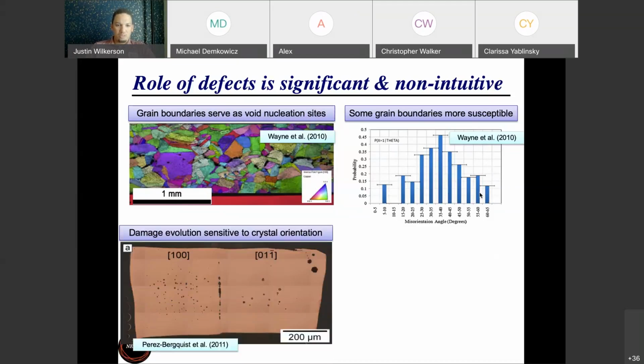Here's a spall experiment that was done on a bicrystal copper, which was pretty cool. So you have two crystals, and the shock comes from the bottom up. On the left-hand side, you have a crystal in which its 100 principal lattice direction is aligned parallel to the shock direction. And then on the right, I have an angle that's tilted from that. And what you can see is that you get different damage in each grain. Over here in the 100 side, I have more voids, but they're smaller. And then here in the tilted case, I have fewer voids, but they're bigger. And then this middle region here is the grain boundary between those two crystals. So you can see you get the most damage along the grain boundary itself.